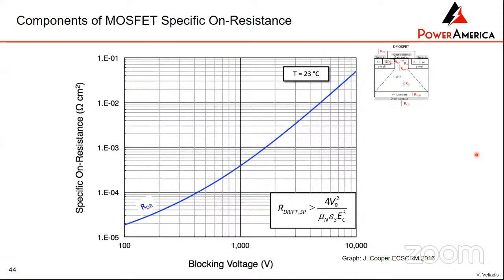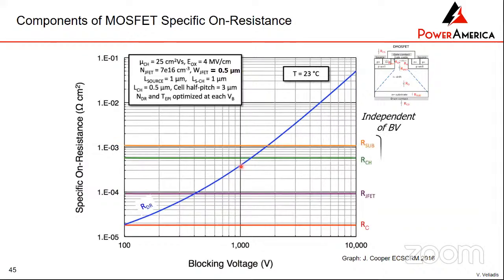And this is a graph that shows you the resistance of a silicon carbide MOSFET as a function of voltage. You can see here, for example, if you want to make a 1000 volt device, then the resistance of this drift layer is shown right here. And then here are the other contributions in the overall resistance of the device. So this is the resistance of the substrate, which is down here. You have the resistance of the channel of this area here. You have the resistance of the JFET, this narrow corridor here. And then you have the resistance of the contacts, the source contact, the drain contact, the gate contact.